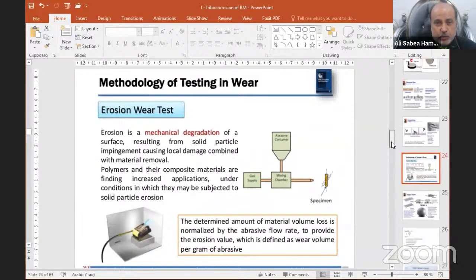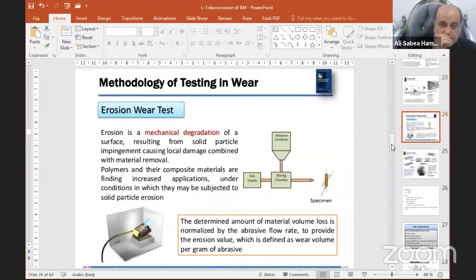Methodology for testing wear. The erosion wear device determines the mechanical degradation of a surface resulting from solid particle impingement causing local damage combined with material removal. The determined amount of material volume loss is normalized by the abrasive flow rate. The flow rate is very important for erosion wear, to provide the erosion value, which is defined as wear volume per gram of abrasive.